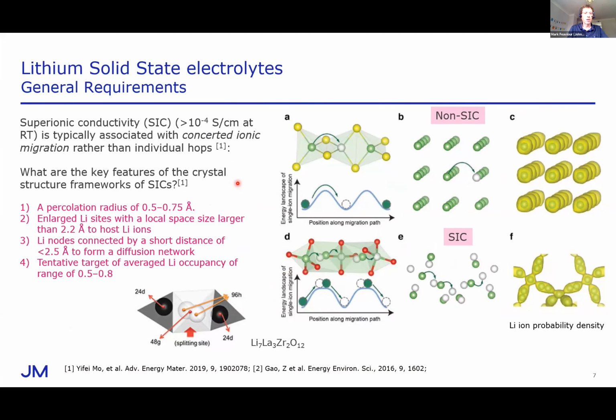Some work by Yifei Mo and co-workers in the States identified 4 primary properties of the crystal lattices that impart superionic conductivity, and they've listed them here. I won't go through them, but some of the most interesting ones were the presence of enlarged sites in the lattice that can accommodate Coulombic repulsion between nearest neighbor lithium ions and establish a sort of variation on the local location of the lithium ion in that site. But anyway, as a consequence, all these things come together to impart this superionic conductivity, which is really what we're after in a decent solid state electrolyte.